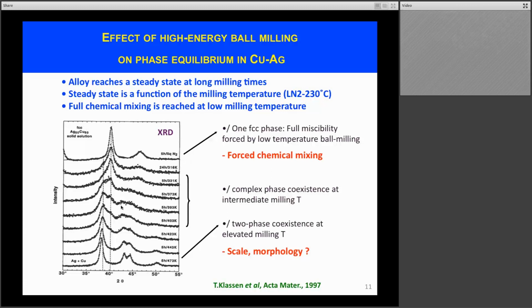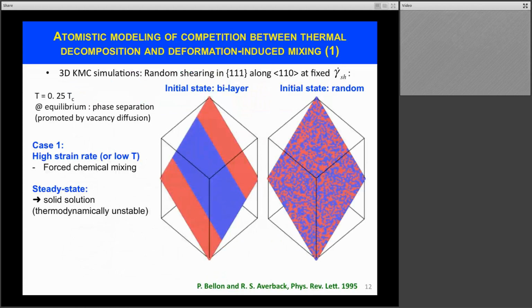What we see is that in the middle there are some complex phase coexistence, but this is difficult to analyze just from X-ray diffraction. And to further improve our understanding of these processes, what we have done with Bob Averbeck is to use simple atomistic simulations to better understand what may happen or could happen in a system such as copper-silver. So here we take a system that wants to phase separate, comprised of blue and red atoms.